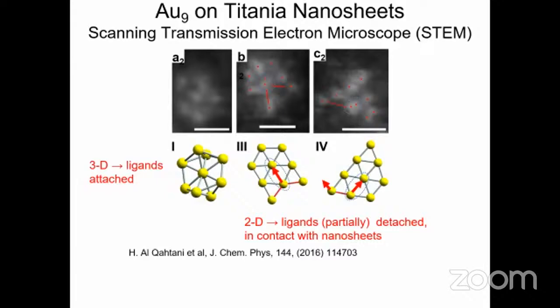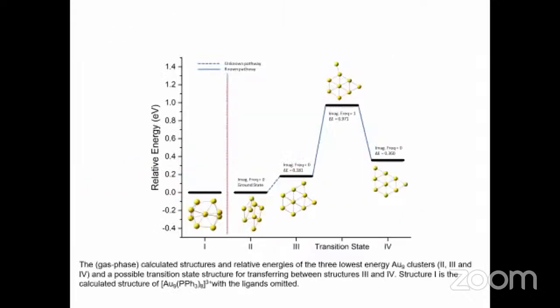And this is another image of the same gold nanocluster. And we compared it with the DFT calculation, the density functional theory, where we have this kind of structure, actually at the lower relative energy. We have it with the ligands, and once they attach, we have it in 2D. That means when we deposit this gold nanocluster, it changes in terms of the deposition. There is one structure, the isomer, which we couldn't find because it is a transition state, and it's hard to visualize by the STEM.